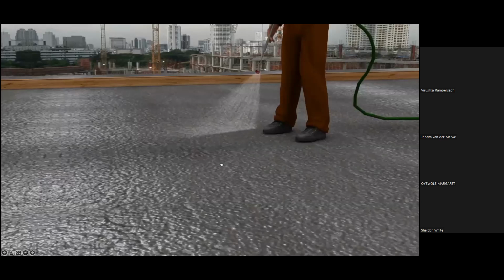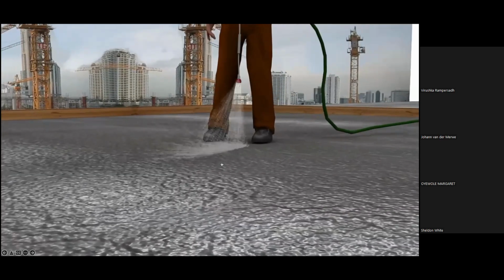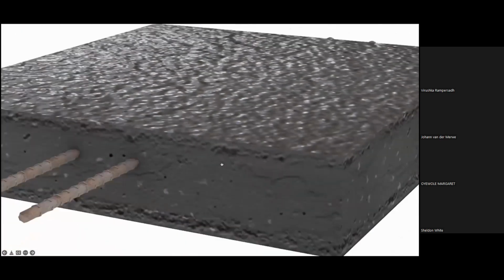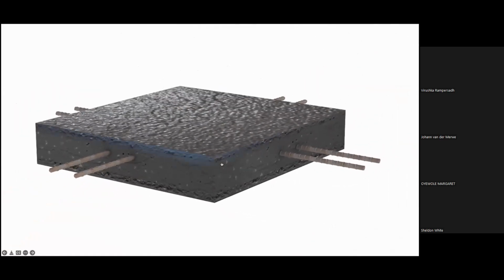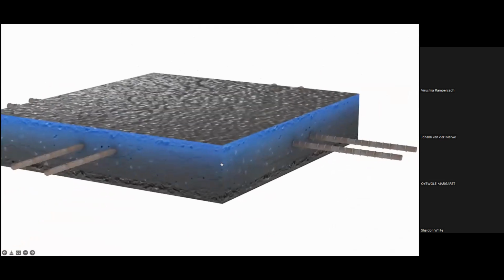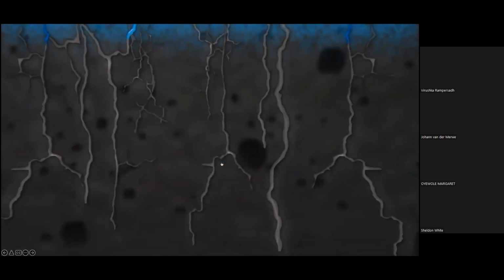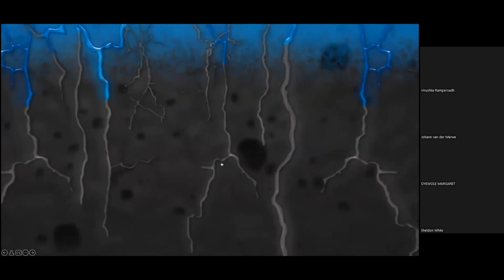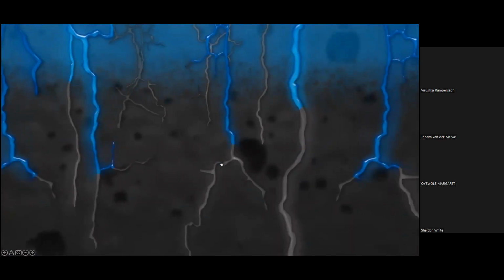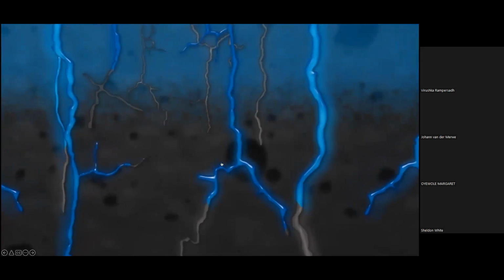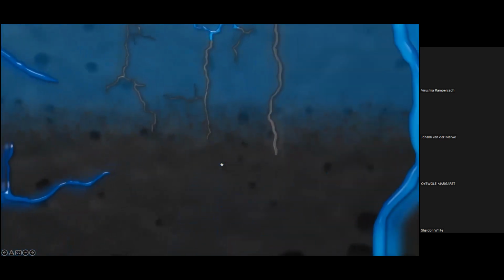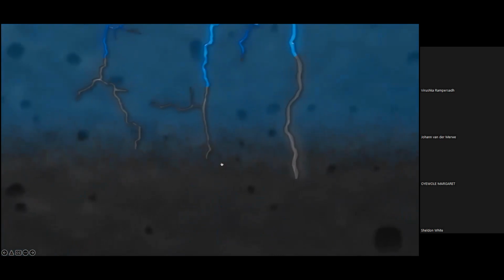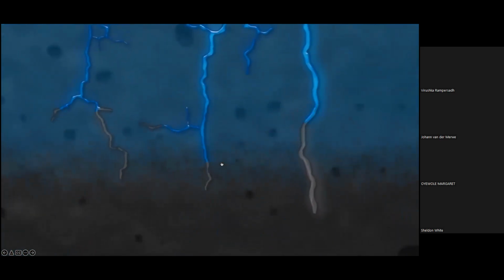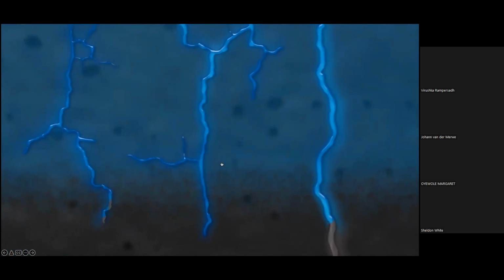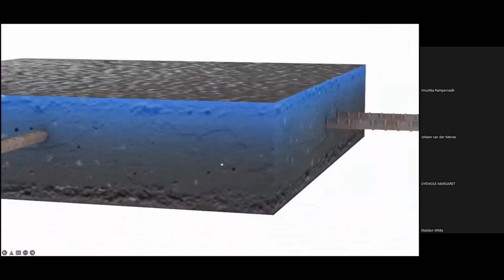This is just a quick little cartoon video demonstrating how it's applied. It's applied to the surface, penetrates into the concrete deeply, where it reacts and closes the void space with that pozzolanic reaction that we talked about earlier, CSH. You're essentially closing void space with more concrete. In fact, you're going to see in a few minutes a scanning electron microscope image where you're not going to see a foreign substance in the concrete. The colloidal silica changes forms. It reacts and turns into CSH.